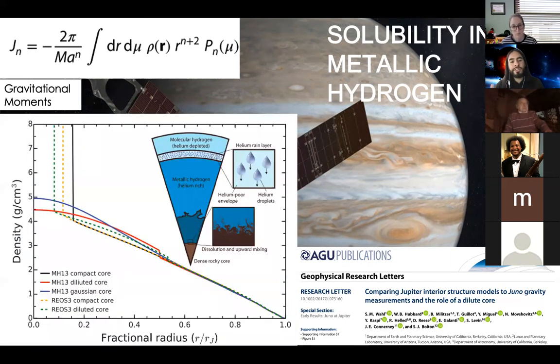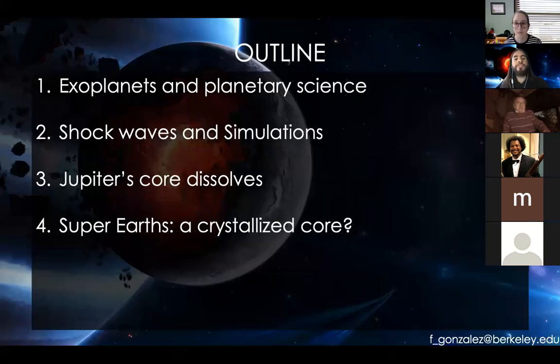And the most recent studies indicate that the measured gravitational moments can be explained if you assume a profile that does not sharply end in a solid core, but considers a core that is diluted. That is, a diluted core density profile is compatible with the measured gravitational moments. So that's an indirect evidence that we have that the Jupiter core is dissolving. And this is really exciting. So it means that we are on the right track with our simulations.